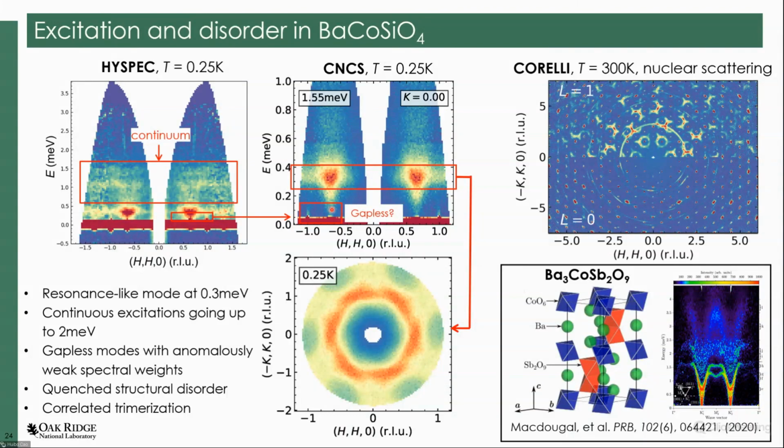The weak excitation is at low energy, so it is gapless, but it is extremely weak. So the feature we notice is mostly a motif excitation, more like a triangle excitation together, or maybe we can call it toroidal excitation, toroidal moment excitations. The modeling we are still working on, because we notice some details when we look very carefully at a lower scale in the reciprocal space plot. Beside the Bragg peaks, we also see some diffuse scattering that is related.